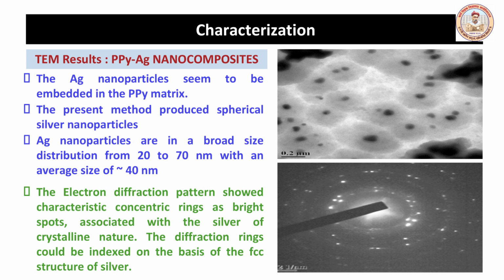The TEM images of polypyrrole silver nanocomposites are shown over here. It is evident from the images that the Ag nanoparticles seem to be embedded in PPY matrix. The present method produces spherical silver nanoparticles. Silver nanoparticles are in broad size distribution from 20 to 70 nanometer with an average size of 40 nanometer. The electron diffraction pattern shows characteristic concentric rings of bright spots associated with the silver crystalline nature. The diffraction rings could be indexed on the basis of FCC structure of the silver.